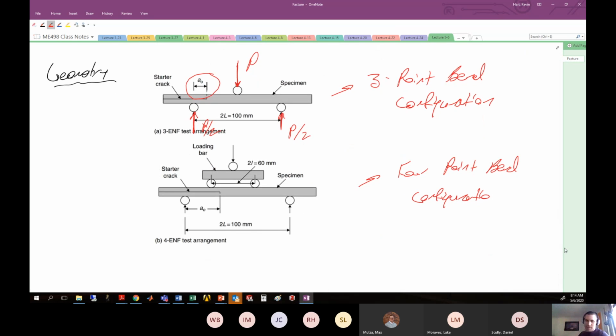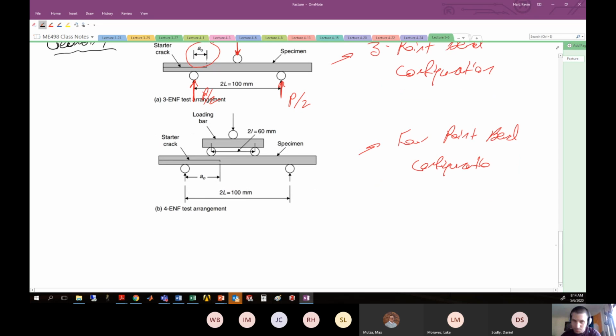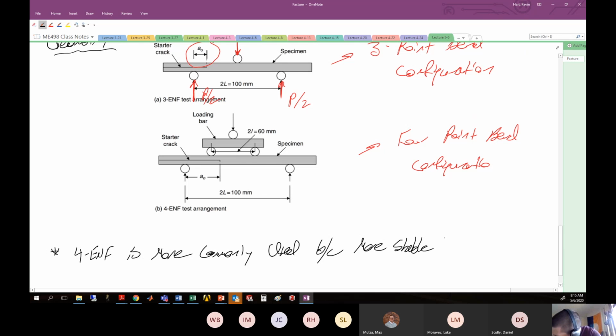So you can do this in 3-point bend, you can do this in 4-point bend. 4-point bend is more common because of how the stress distribution is distributed inside of the piece. Okay, but generally they're more or less the same. All right, so these are the general samples and what they look like. Okay, back to it. The same idea holds here: when we apply this bending load, we're going to supply energy to the sample. So analysis is more or less the same. I'll say 4ENF is more commonly used, and that's because of a more stable stress state.